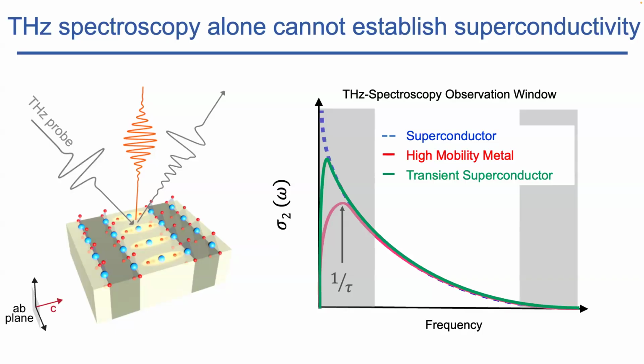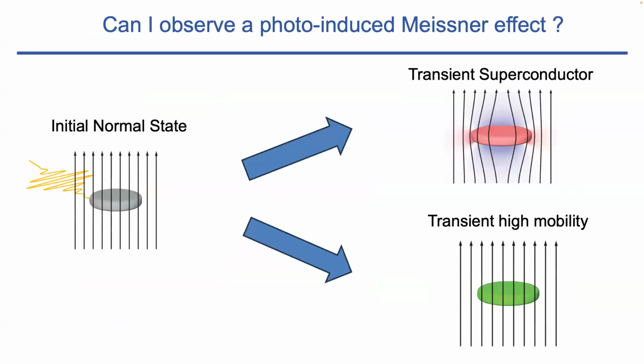But if you cool it down in a magnetic field, I'm reminding you of things that everybody knows, but I had to go through the textbooks again when we started working on this. If you cool it down in a magnetic field, then either the material is a perfect conductor, in which case the magnetic field will be stabilized, or the material becomes a superconductor, in which case the material will expel the magnetic field. So if I do the same thing, I embed my normal state in a magnetic field and photoexcite it, then the two possibilities are it's either a transient superconductor, therefore the magnetic field will be expelled, or it's a transient high mobility metal, in which case the magnetic field will be locked in place, even more rigid than it used to be. So these are two radically different things.